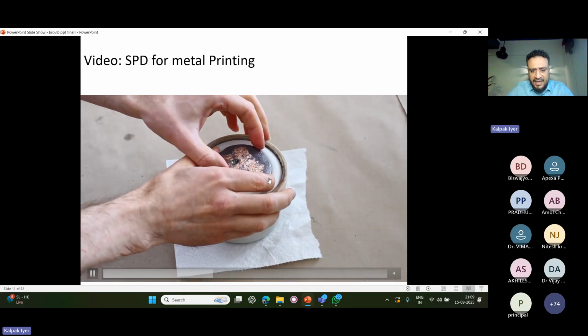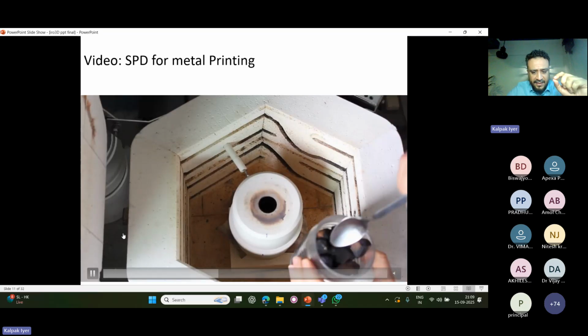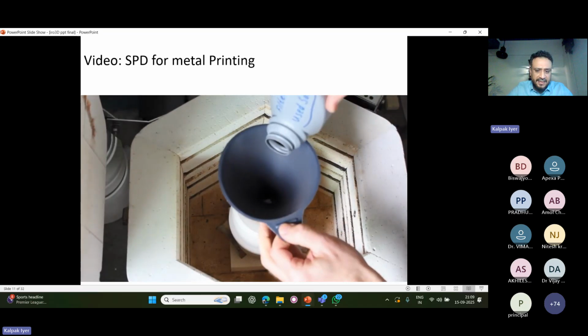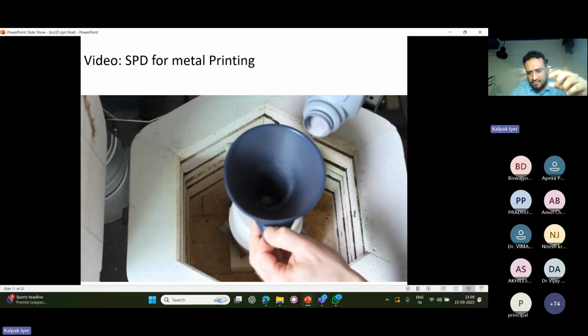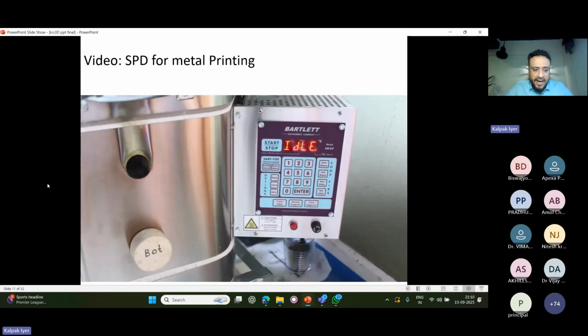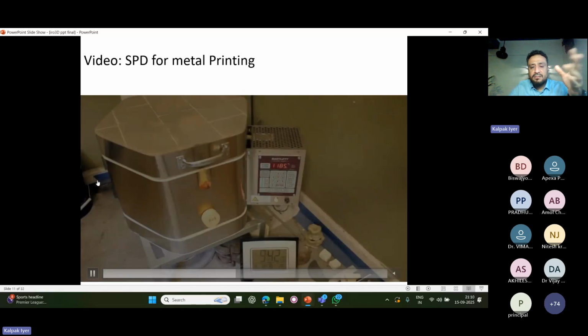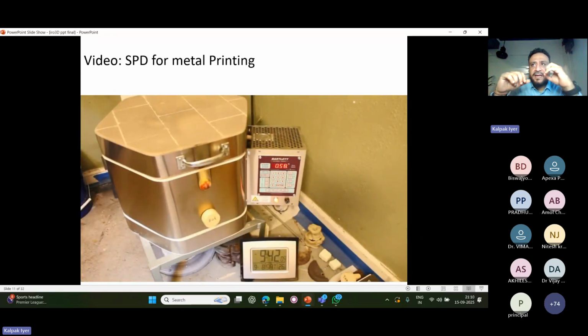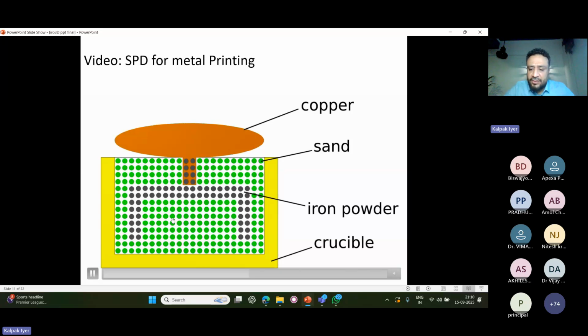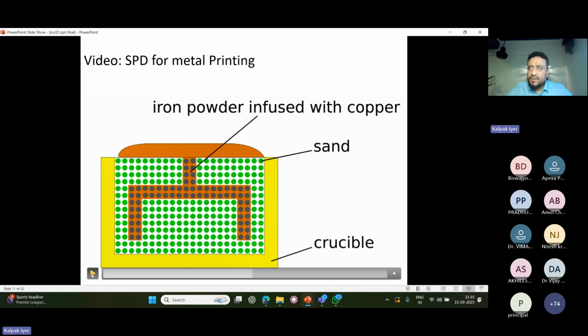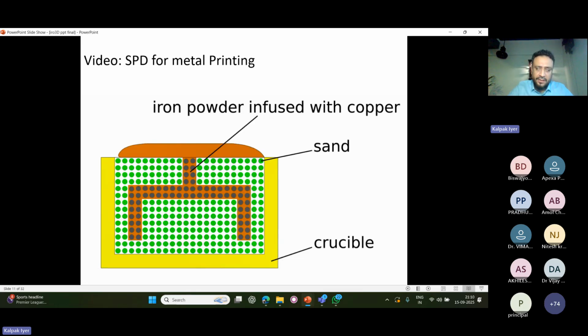Okay. Once this is done, you close the lid and add some reducing agent. So reduction has to happen. The build powder, iron powder in this case, like all metals, tends to oxidize and have an oxidized layer, so iron will have iron oxide on its outer boundary. If the copper melts and drains from the runner into the actual print, because iron is not available, only iron oxide is available, and these oxides are not wettable. So we need to remove the oxide layer. That is why we added the carbon, the coke. What the coke does is it aids in the reduction reaction. I'm oversimplifying it, but that is the long story short. The reduction reaction is initiated, and the iron oxide layer on the iron powders is reduced, so that elemental iron is available for alloying and diffusion between the copper and the iron.